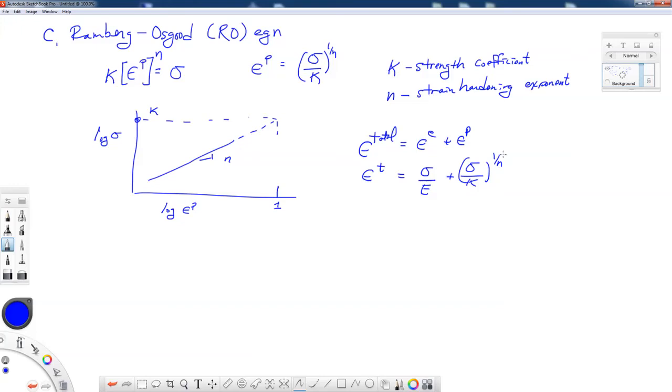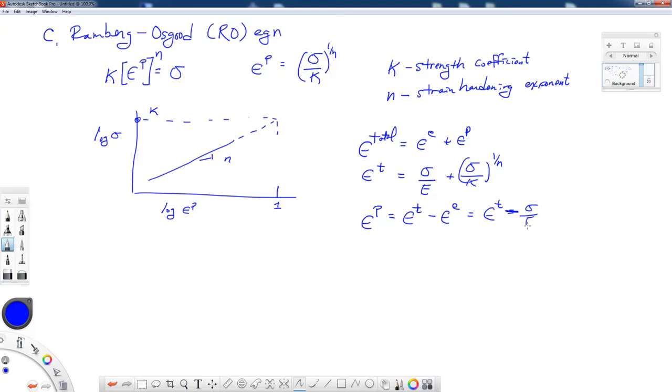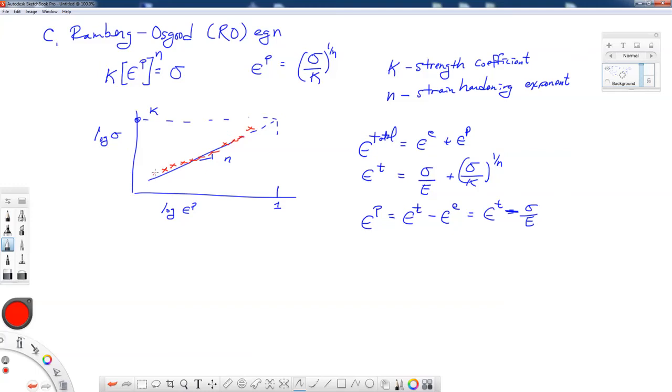Now, if you plot the plastic strains, and the way you're going to have to find plastic strains is you'll think the plastic strain is equal to the total strain minus the elastic strain. What you'll find is that these data points aren't exactly on a straight line. They're pretty good. You know, they might deviate here a little bit. But the exact value of n and k may be different depending on your interpretation of how to fit this data to this functional form. If you fit this set of data, you might get a different set of constants, k and n.